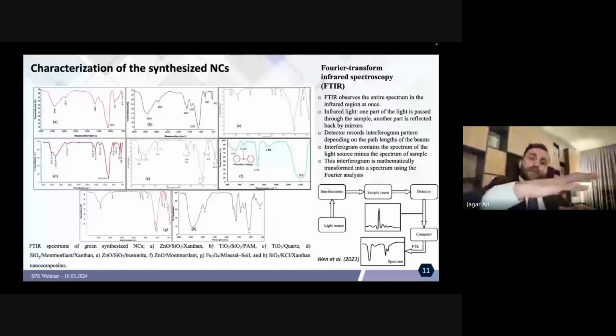But pH, for example, when it is above 11, it will give you nanoparticles, but when it is less than 5, it will give you maybe nanotubes. So you should be very careful about the stability of pH and temperature. These are some plants that we used in our work, and here we have the procedural steps that we consider to prepare ZnO-SiO2 xanthan from the pomegranate seed extract.